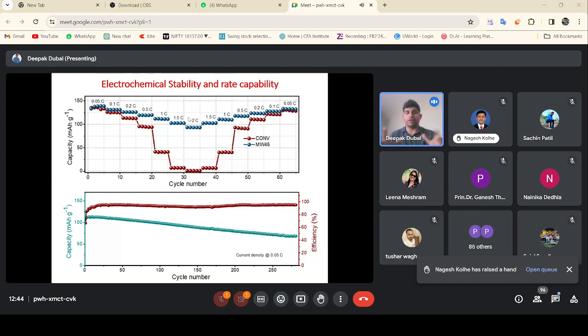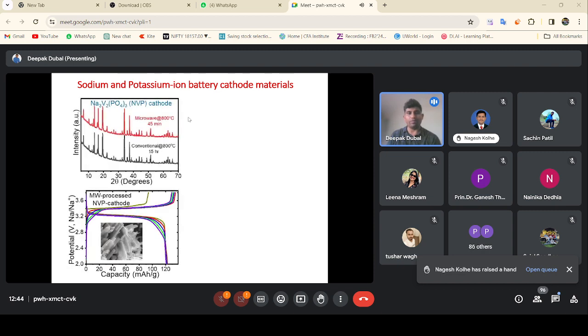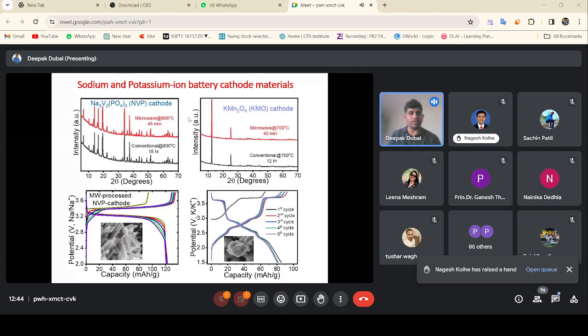We are still trying to build an in situ X-ray diffraction furnace, a furnace which we can fit into the X-ray diffraction, so that we can see how the material is growing with respect to temperature. But so far the results are very, very impressive. We also wanted to synthesize different types of cathode materials, not only for lithium-ion battery chemistry, but we explored the synthesis of cathode materials for sodium and potassium batteries. And the results are very nice. We could synthesize any type of battery material using the microwave in a very short time. And the performance is very interesting.